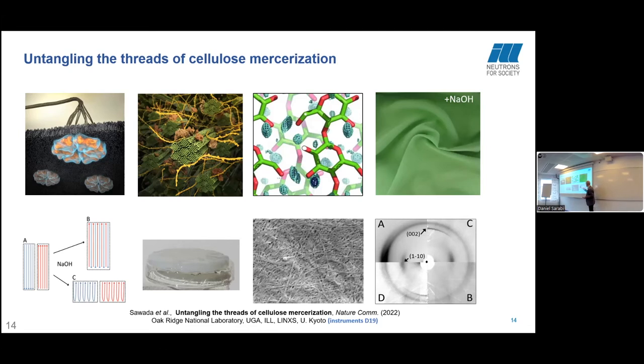So this is fiber diffraction data collected using neutrons from mercerized cellulose. Diffraction data collected from a sample with all deuterated cellulose, a sample with all hydrogenated cellulose, and a sample where we had equal mixtures of nanocrystals which were deuterated and hydrogenous. We measured the intensities, and it was clear that this is the mechanism which actually happens within cellulose as you mercerize it. That's really cool.